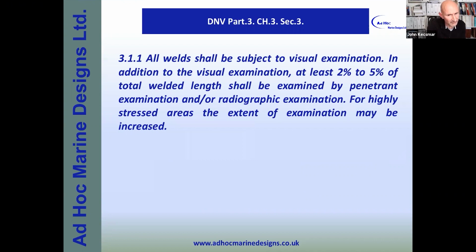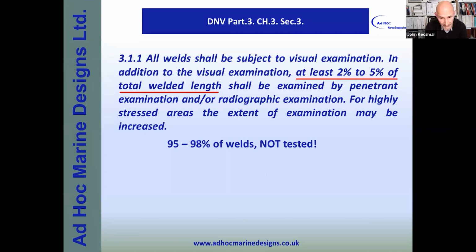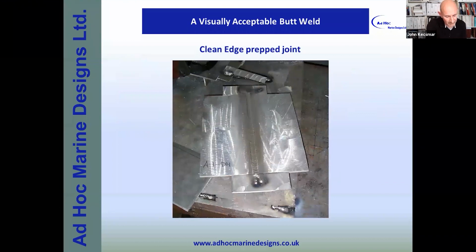So if we look at what class says about such things, here's an excerpt from DNV. It's all about visual examination and radiographic examination, and it refers to having 2% to 5% of the total weld length tested. What I take away from this is not the 2 to 5%, it's actually the opposite. I see it as 95 to 98% of the weld not tested. And when you consider that most of the ship's structure consists of fillet welds, how are you going to x-ray them? You can't. So you're relying upon purely visual examination and at times perhaps a bit of penetrant testing, because only butt welds can be x-rayed.